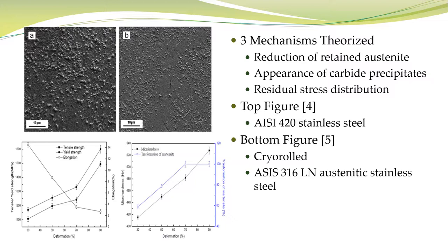The carbide precipitates increase wear resistance due to the fact that they act as ball bearings during wear and roll instead of slide, decreasing the amount of friction between the two surfaces and decreasing the amount of shear stress that the material feels during wear.